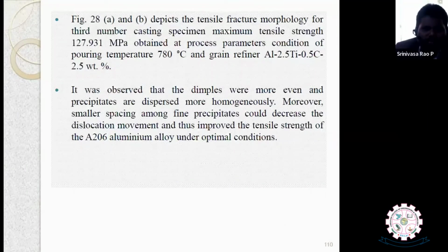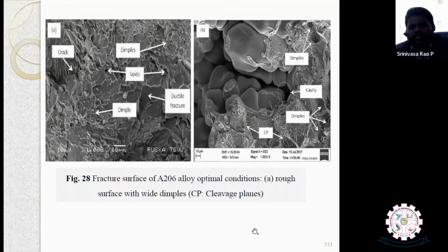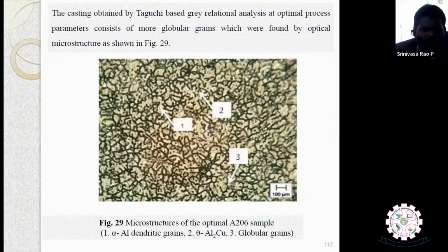Okay. So at that, SEM analysis for optimal conditions of the tensile specimen. You see the voids and dimples, ductile fracture dimples. This is the cavity and dimples. And finally, we have carried out the microstructure. We see the grains are in the form of globular, meaning equiaxed grain type structures.